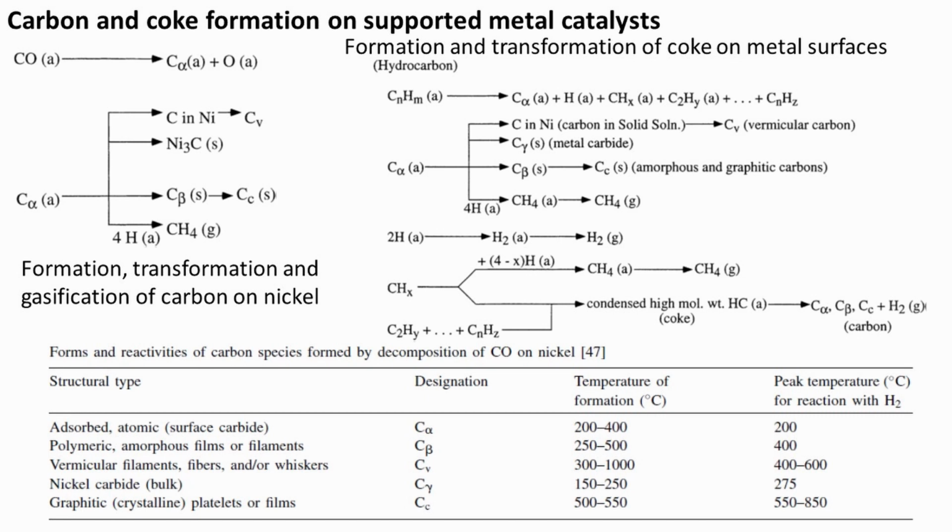The more reactive amorphous forms of carbon formed at low temperature are converted at high temperature over a period of time to less reactive graphitic forms. The rate at which deactivation occurs for a given catalyst and reaction depends greatly on reaction conditions, especially temperature and reactant composition. A fundamental principle for coke-insensitive reactions on metals is that the deactivation rate depends greatly on the difference in rate of formation and gasification of carbon and coke precursors.